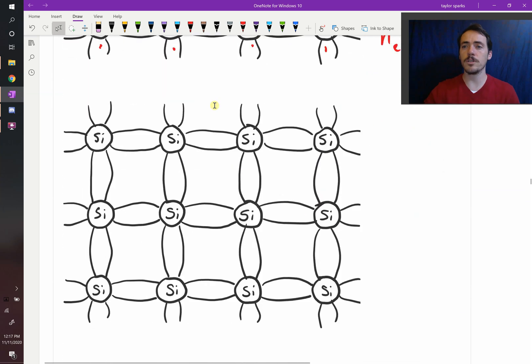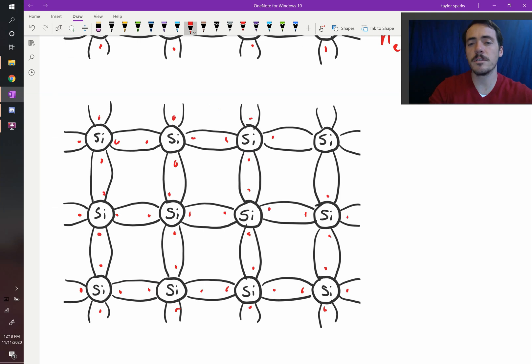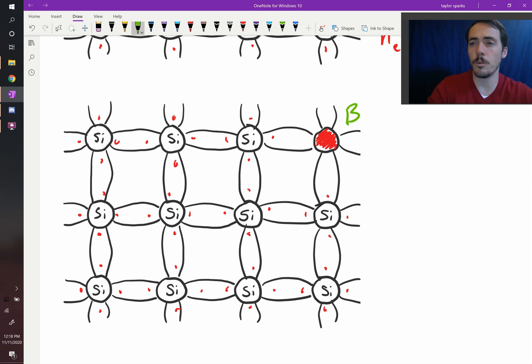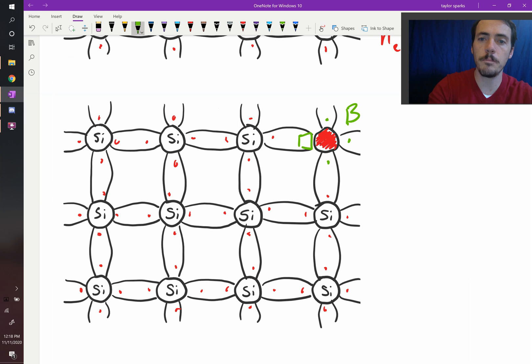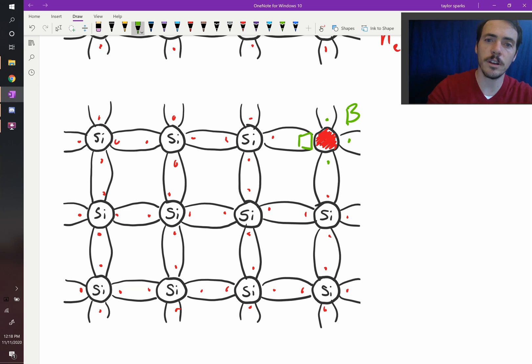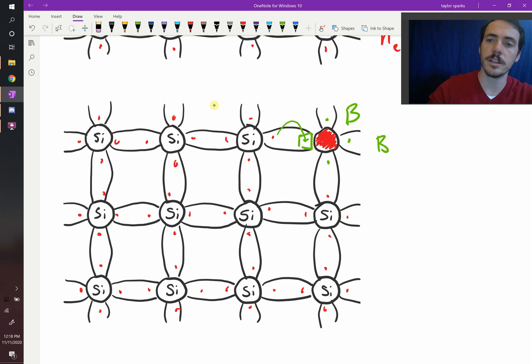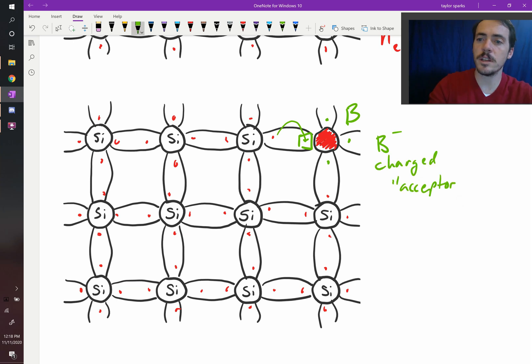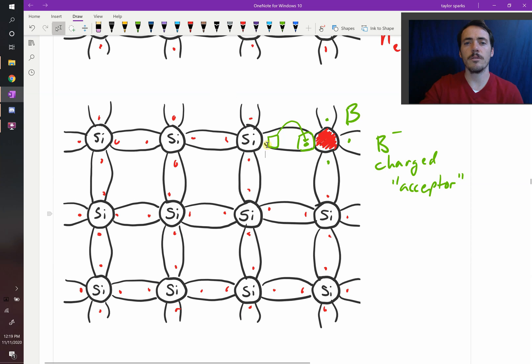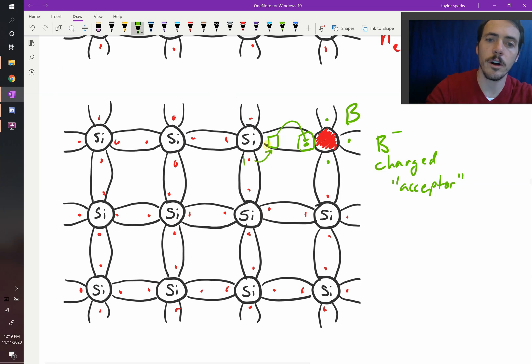You could dope it another way. Instead of phosphorus, let's put something like boron on the silicon site. If we put a boron atom there, it only has 3 electrons — it's a group 3 element. So it has a built-in hole in this bond, and that unsatisfied bond is just waiting to have an electron come fill that spot. If we take a nearby electron and it fills that spot, we end up with boron minus — it's become a charged acceptor. It has accepted an electron, and in doing so, it created a hole for the nearby silicon.